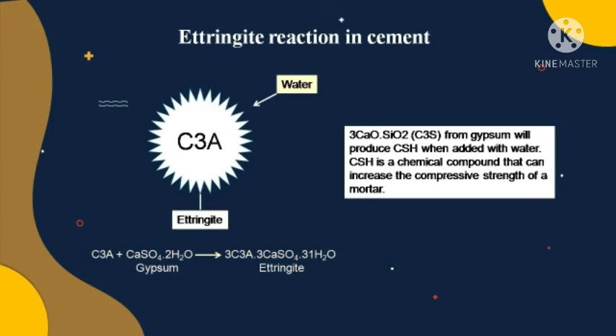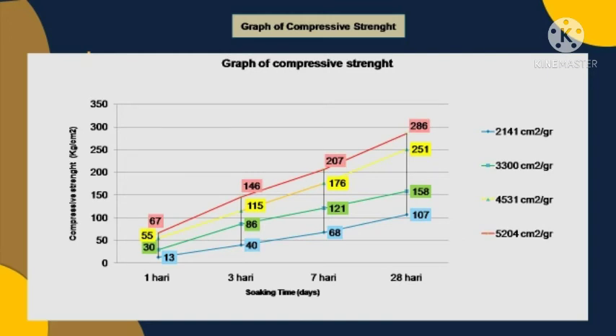As for the reaction that occurs when water reacts with a mixture of tricalcium aluminate content from clinker with calcium sulfate hydrate from gypsum, it will form a new compound in the form of tricalcium aluminate, 3 calcium sulfate, 31 hydrate, or commonly called ettringite. So the finer the cement particles, the faster the water reacts with the compound content. And the next test is the fineness effect on compressive strength.